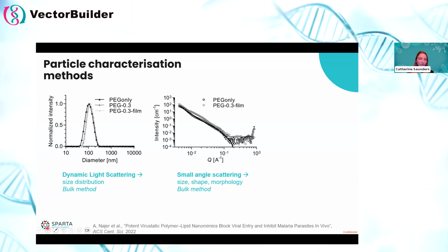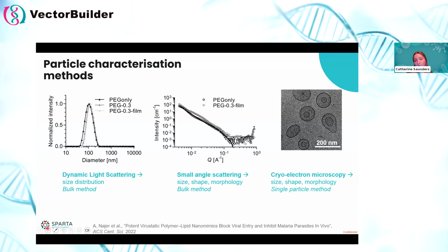However, as I put here, these are both bulk techniques, so they're looking really at the ensemble average. And so it's always important to then employ single particle techniques as well. So what was also included was some cryo-electron microscopy, which is really visualizing the single particle morphology. It showed some quite interesting vesicle structures, which were then revealed.